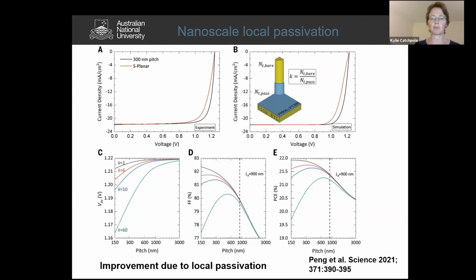And particularly what we see is that increase in fill factor by having the combination of the passivated areas and the unpassivated areas. So again, that provides that balance between the areas where you have reduced recombination, but it also allows you to get that good electron transport into the bare regions.